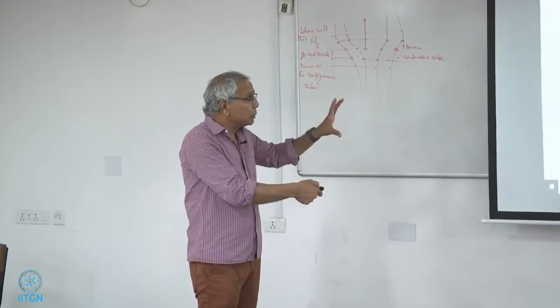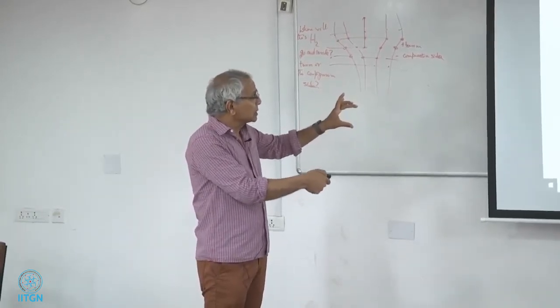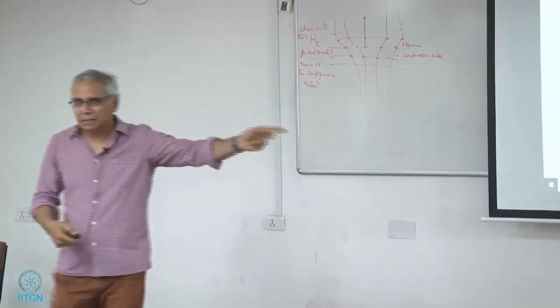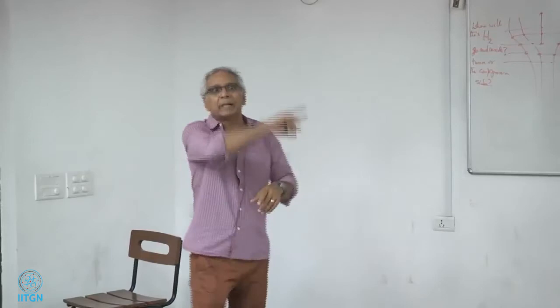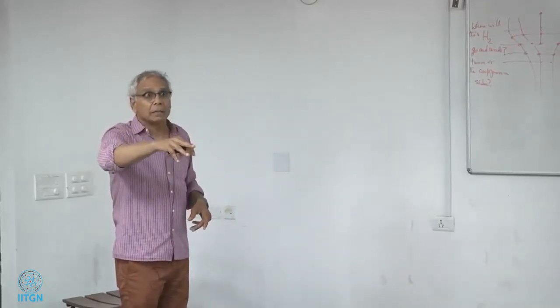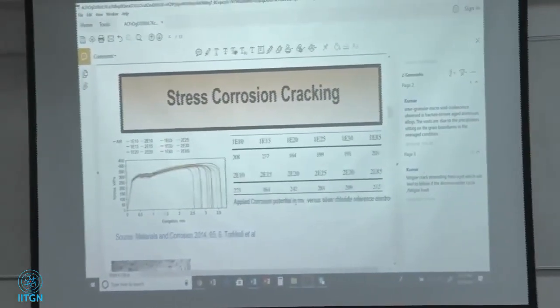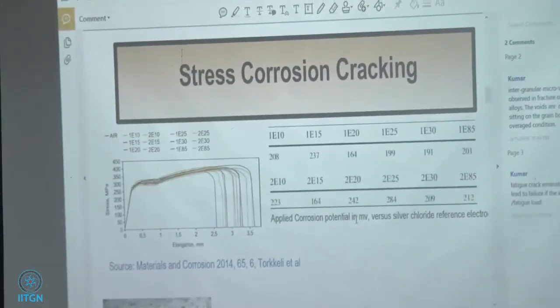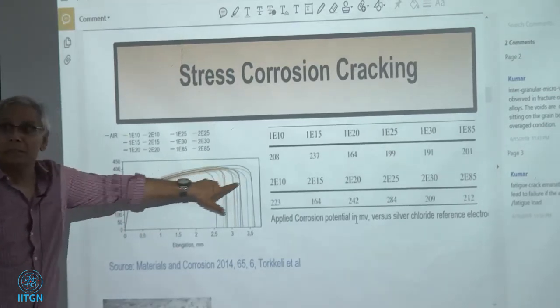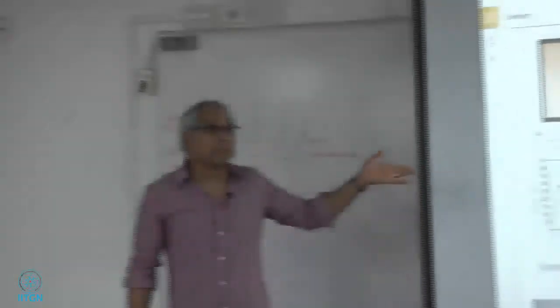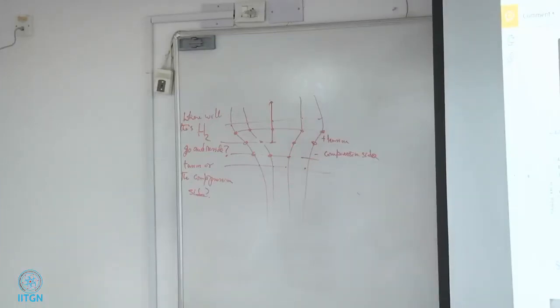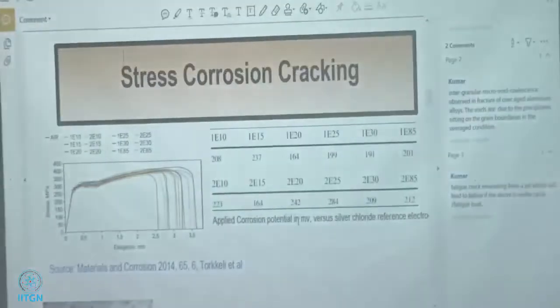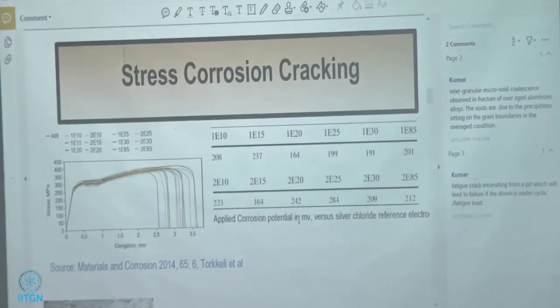So here is a common test that we all do for stress corrosion cracking. Simple tensile tests, elongation stress at different strain rates. Just like we talked about before the break. Right? Before the break, we did fracture strain as a function of strain rate. And Kumar had a question, a comment rather, not a question, as to how it's getting affected. So here also you can see, I'm not going to go through these 100 lines here, but it's going to reduce as a function of time. So this is much not faster, but cheaper, because if you're doing it at a very slow strain rate, it's going to take some time. Okay? But these tests were done in air at slow strain rates.